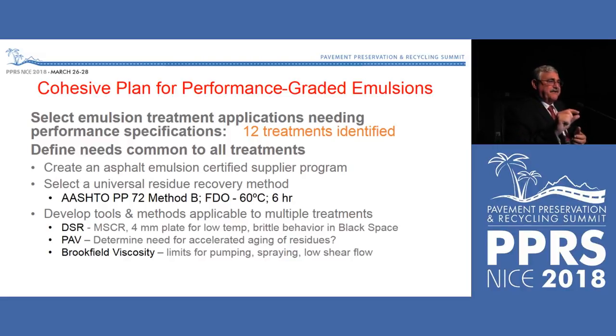We're using very, very thin film that gets us residue in 6 hours instead of the 48 hours required for the European method, so we can turn around information faster, and that's primarily because we're turning over emulsion tanks every day when there are chip seal crews coming through. We can't wait weeks for this information. We have to find ways to speed up our recovery process, and this is one way of doing so, but it delivers very little material, because the film is thin, so we can get the water out, but that means we don't have much residue to test.